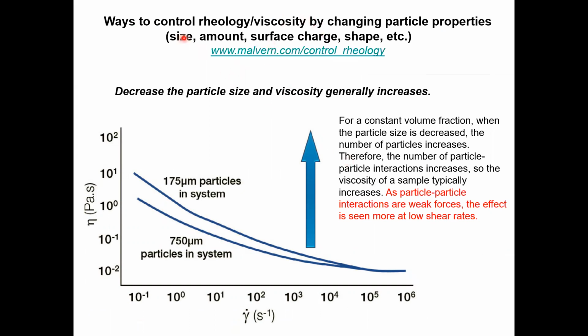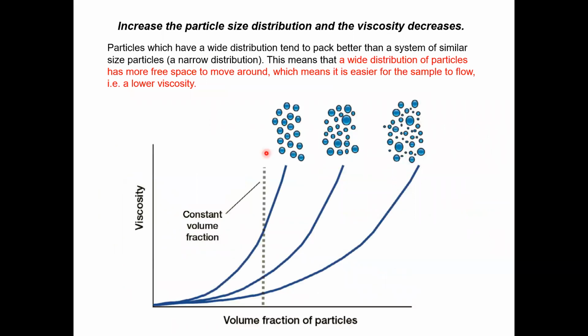Other parameters that you can use to control the viscosity are the size, the amount you add, surface charge, shape, etc. So you can see here is an example of using two different size particles, 750 micron and 175 micron size particles of a given material as a function of the straining rate. You can see at lowest straining rate, viscosity variation can be substantial between the two. But as you go to higher straining rate, you can overcome the size effect. The particle-particle interactions are weak forces, so the effect is dominant at low straining rate and not so dominant at high straining rate.